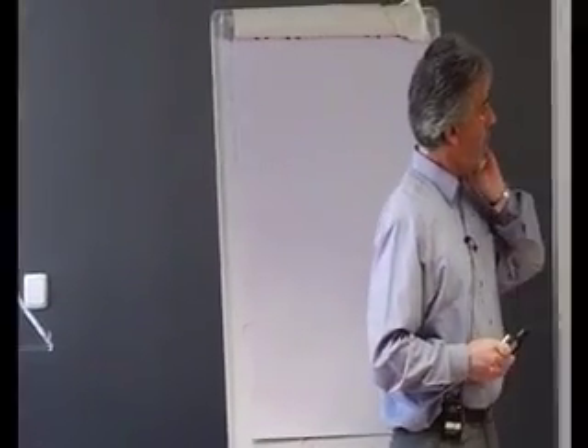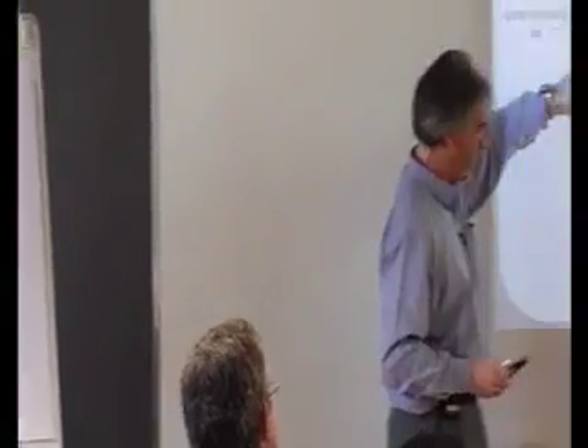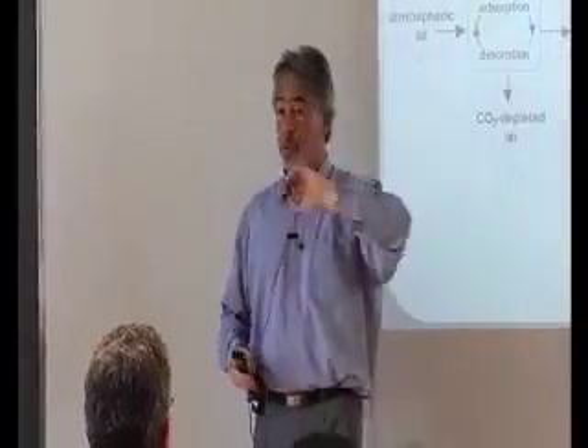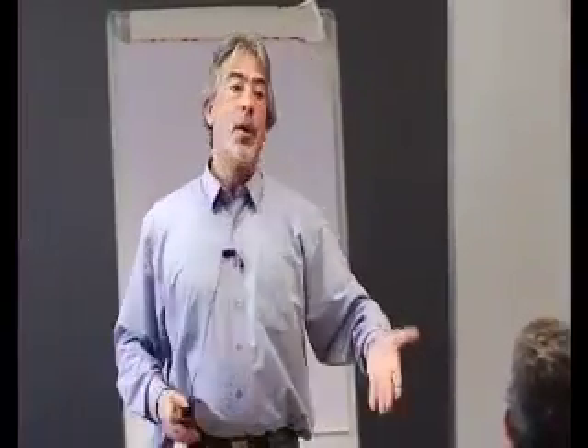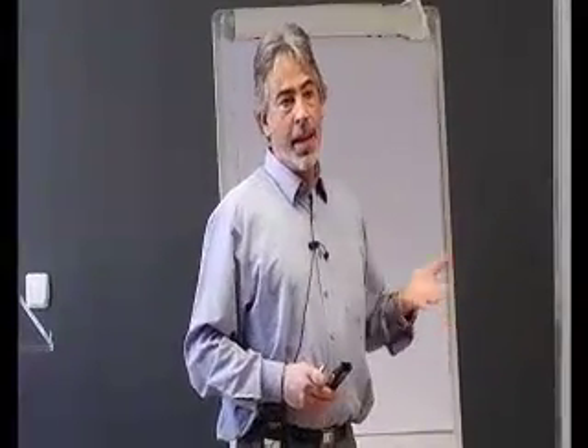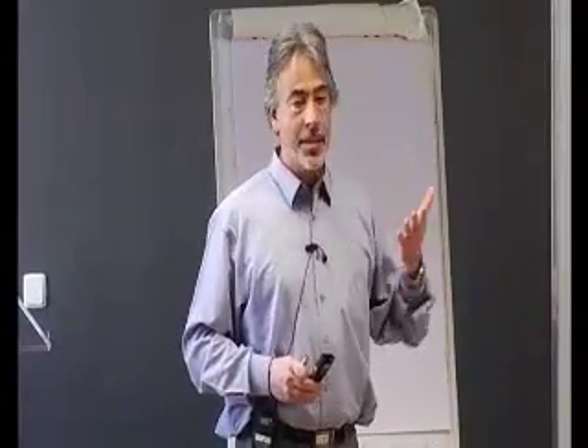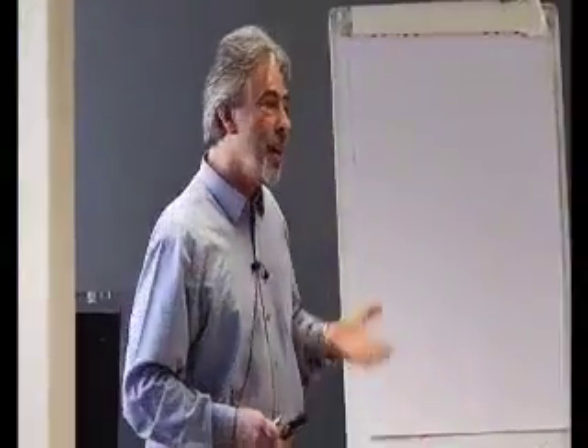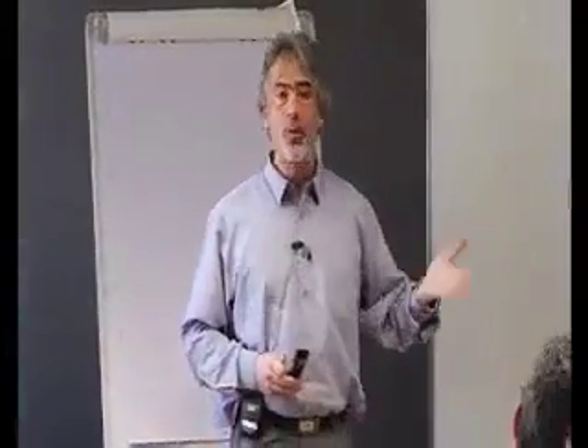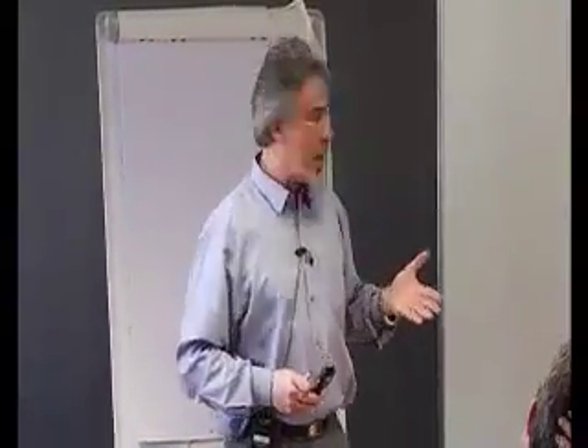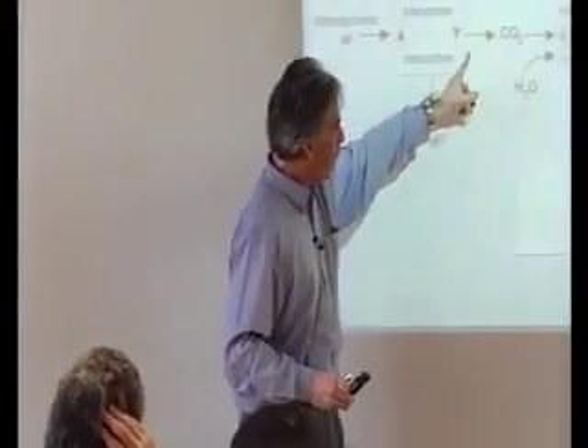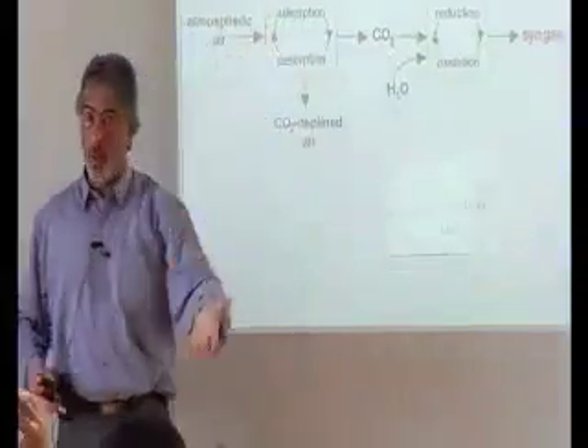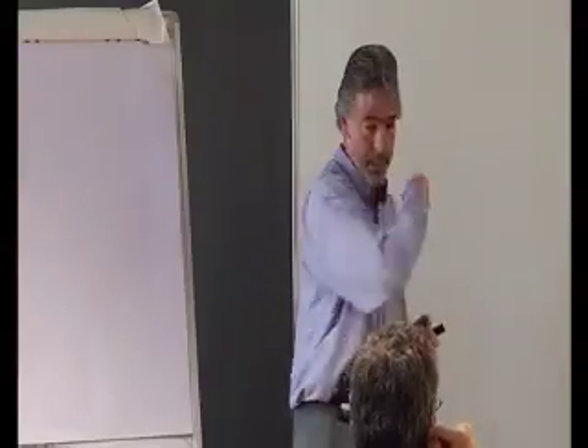Very interesting, we also discovered a few weeks ago that as we do this process of absorption and desorption to collect pure CO2, we are at the same time collecting pure water. Even if we use dry air with a humidity of 0.3%, we still have 10 times more water content than CO2 content. And when we do the desorption, we obtain a mixture of CO2 and steam. We condense the steam, we have pure water. Very interesting, because if we want to have this process, for example, in the desert of Andalusia, there water is a problem.